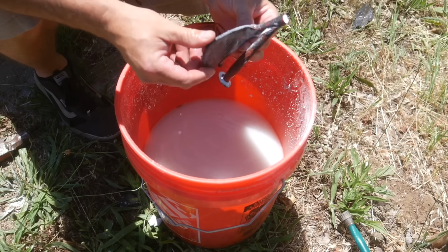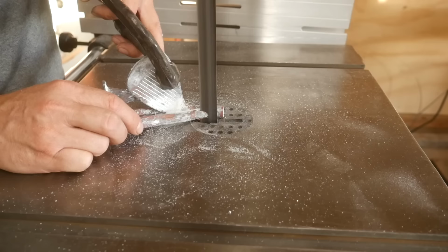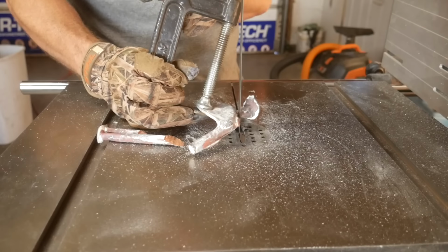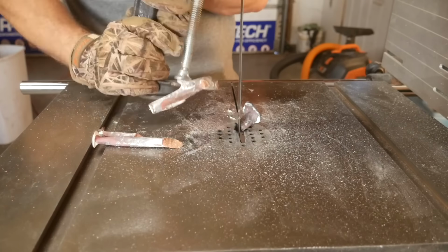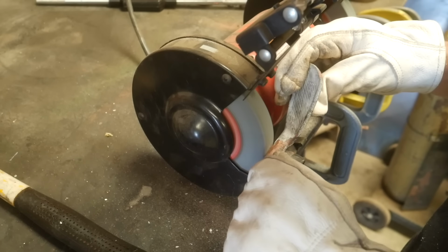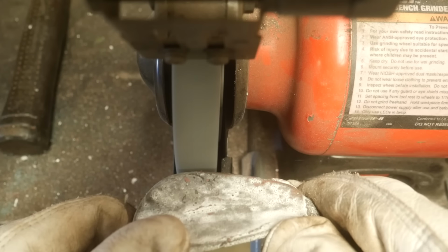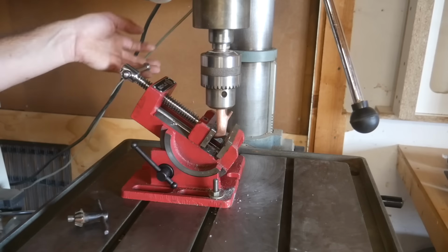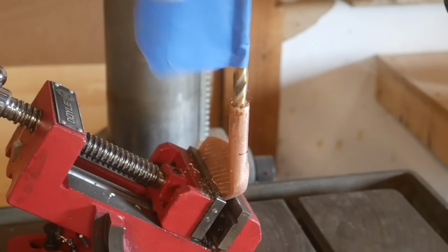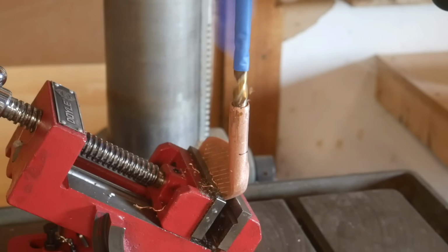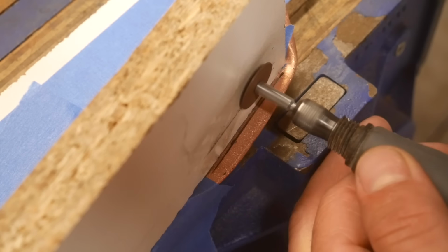The casting turned out solid, relatively clean grooves and no major flaws, and now we just had to clean this thing up and get it glued onto a shaft. We cut off the vents on a bandsaw, cleaned up those cuts on a grinder, and drilled out the hosel since the casting didn't go to full depth. We had to do a little bit of groove work with the Dremel just to clean up the bottom groove a bit.